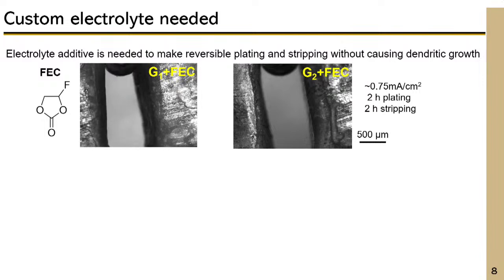As you can see, the videos are running, and it's not forming any dendrite. So we got what we wanted. We wanted to stop the dendrites so that this metal can run for a very long time without any catastrophic events. Now, this fluoroethylene carbonate is a very expensive electrolyte, so we're deviating from the fact that we wanted a low-cost battery.